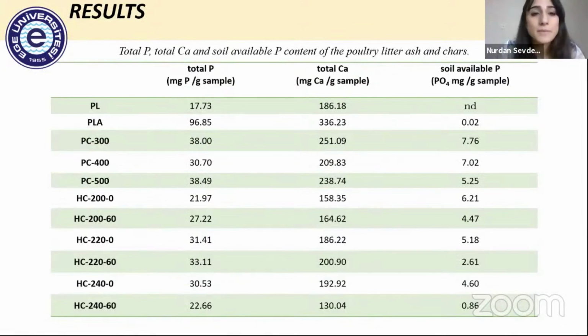We also compare the total phosphor, calcium, and soil available content of poultry litter ash in the chars. I would like to explain soil available phosphor briefly: it defines the phosphor that can be easily taken up by plants, and it is more important than the total amount of phosphorus. As seen, poultry litter ash has the highest phosphorus content, but it has the lowest available phosphor.